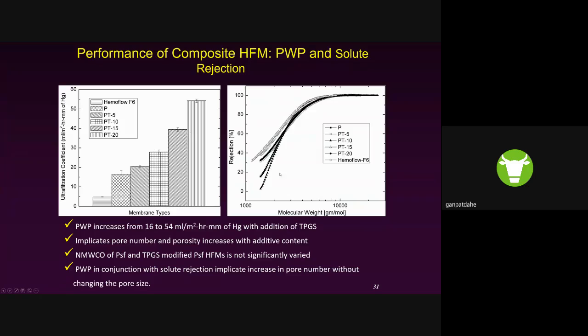water permeability. And this is the rejection plot, and you might have heard about the molecular weight cutoff. That is a very common characterization of the hollow fiber membrane. This molecular weight cutoff is nothing but the molecular weight corresponding to 90% rejection. This is the percentage rejection, and if you draw a line from this 90% rejection all the way here, whatever molecular weight corresponds to that point on this X axis is nothing but the molecular weight cutoff of that membrane.